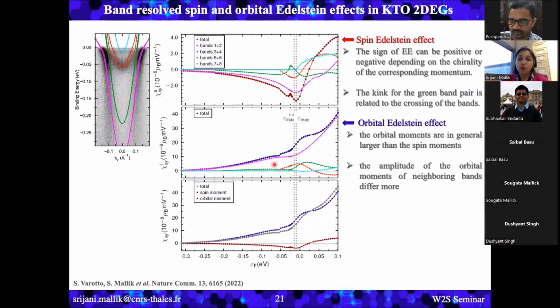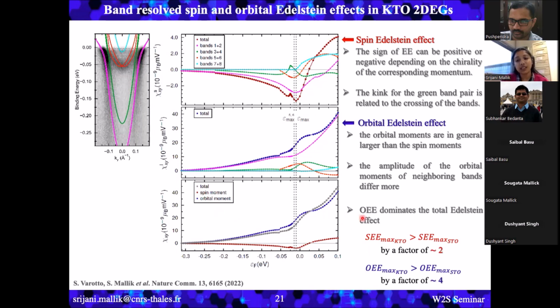And the orbital Edelstein effect shows that they are larger than the spin moments. And also the sign of the orbital Edelstein effect is opposite to the spin Edelstein effect. So when we plotted the total of spin plus orbital Edelstein effect, there is also another compensation effect coming due to this. But despite all this compensation effect, still the spin Edelstein effect with KTaO is larger than the spin Edelstein effect in STO by a factor of 2. And the orbital Edelstein effect in KTaO is larger by a factor of 4 in comparison to the STO 2DEG.